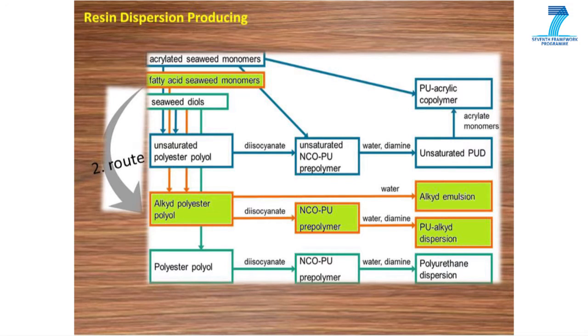Second route is about alkyd resins. The synthesis starts with an intermediate polymer called alkyd polyester polyol. In contrast to the route described above, this polymer contains fatty acids. Further modification leads to an alkyd polymer, which can be dispersed in water. An alternative route is the combination of alkyd resin with polyurethane resins. Therefore, the alkyd polyester polyol can react with diisocyanate to get an alkyd polyurethane hybrid.